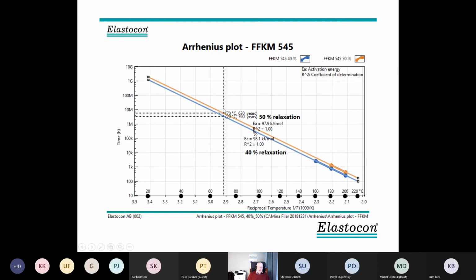Then we can have a cursor here. We can find out the lifetime at say 70 Celsius. And there's quite a difference in lifetime between these two, 40 or 50% relaxation. We can also calculate the activation energy, and we can see the coefficient of determination, how good the line is. Normally we get quite good lines. So in this case, we can get a better estimation of the lifetime of the material. So even this fantastic, at least expensive, material does not last forever.